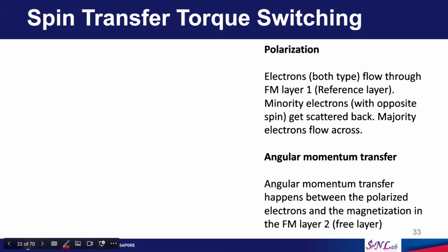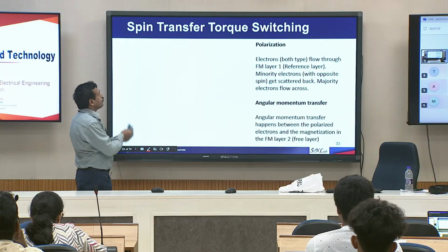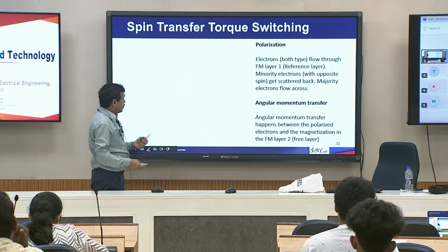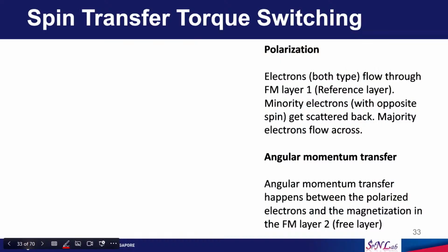So, this was possible because of the 2 concepts that we learnt. First concept is polarization. That means, when we send electrons through a certain ferromagnetic layer, the electrons with the magnetic moment opposite to the magnetization get scattered back, and the electrons with the magnetic moment parallel to the magnetization flow across. That is the polarization concept. Secondly, the electrons which go to the other side of the free layer will exert a torque. So, there will be angular momentum transfer happening. As a result, the magnetization of the ferromagnetic layer on the other side of the reference layer will switch. So, this is basically the spin transfer torque switching.